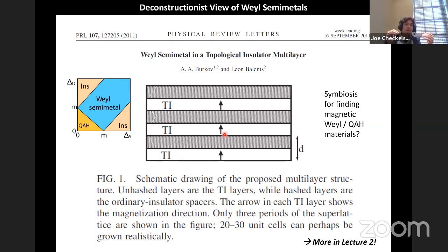And he showed a way, conceptually, of building a Weyl semimetal, basically an ideal Weyl semimetal, by layering magnetic topological insulators together with a type of insulating layer stuck in between. One way of thinking about how this works is that with this insulating layer and also the thickness of the topological insulator layer, you're basically controlling how much coupling there is between these different surfaces, either between the surfaces of the TI or from one TI to the next.